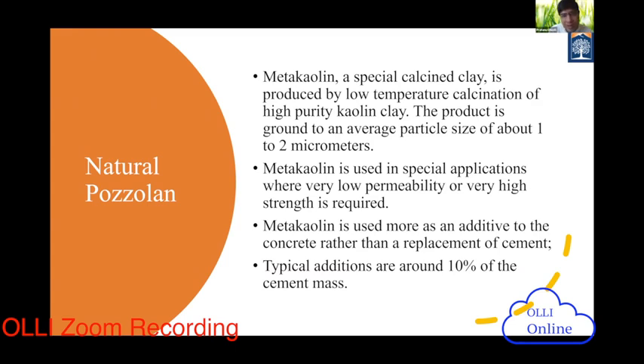It is a special application. We cannot use metakaolin everywhere. Wherever you need very low permeability and very high strength, metakaolin is the ultimate choice. It is used more like an additive material rather than a replacement of cement. Typical addition again is 10%. You do not need heavy amounts. It is a little bit costlier than cement, but overall life cycle cost will be reduced, as you can imagine.